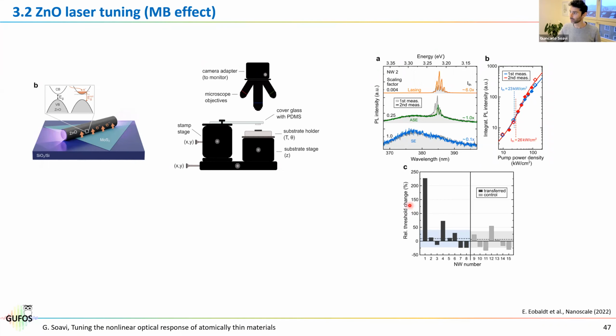Now, we look at the changes in the lasing threshold when we do the transfer. We do it for nanowires that we transfer multiple times and nanowires that we keep in the lab always on the same substrate. Basically the fluctuations look pretty much the same, apart from one case that was out of average, but otherwise it looks like our method doesn't really affect the lasing performance of the nanowires.